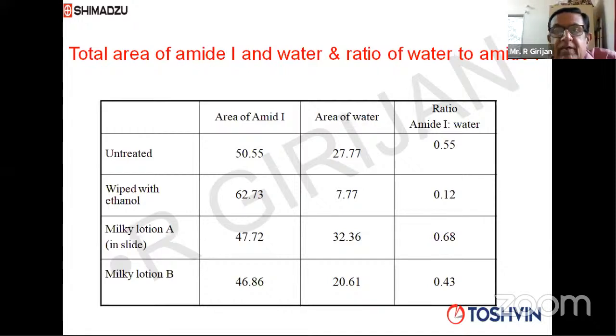There is a specific ratio of amide to water. The lotion which gives you the highest ratio of amide to water is going to be the most effective lotion. For the untreated palm, it is 0.55. After wiping it with ethanol, because your skin has become dry and most of the water is gone, the ratio has become 0.12. Then you applied milky lotion A, it has given a very high ratio, 0.68, compared to the second lotion, which is giving only 0.43.